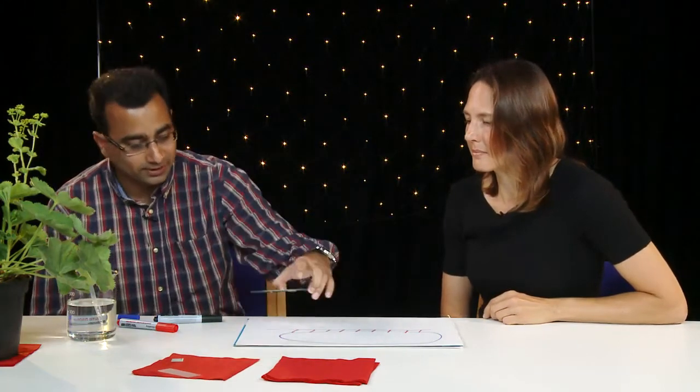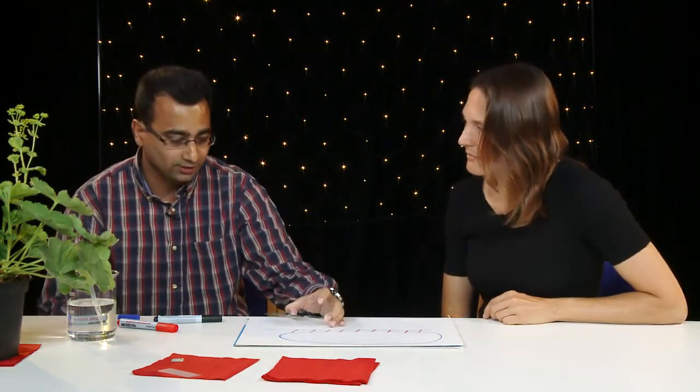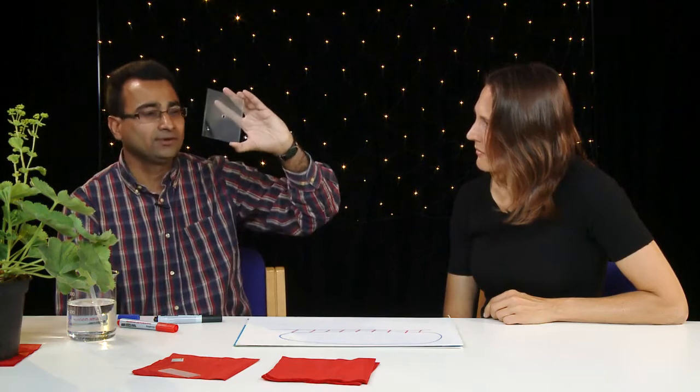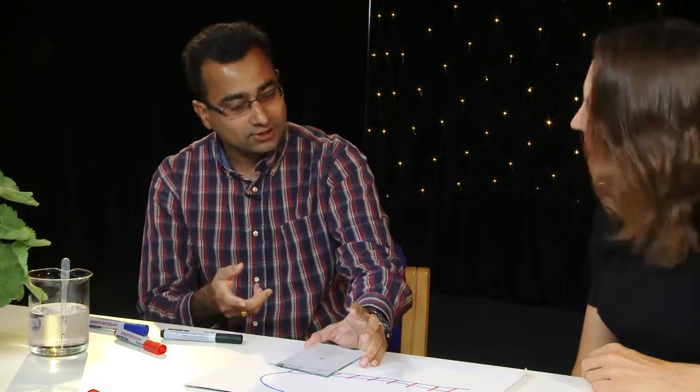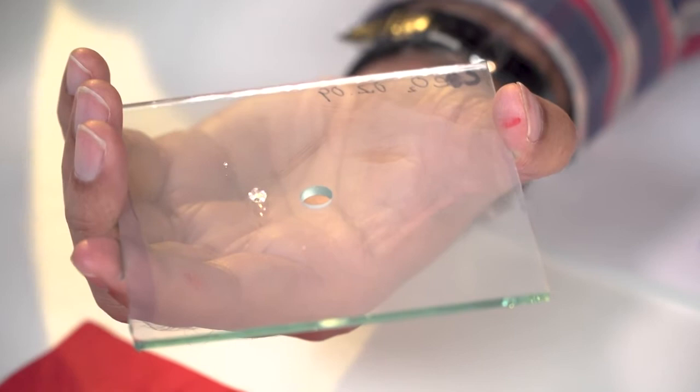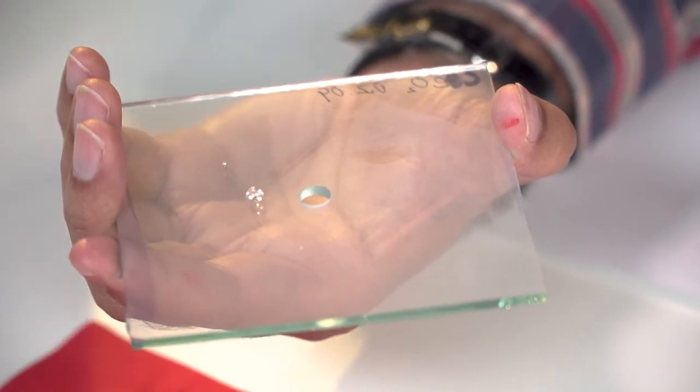So this is an example where we've tried to go one-up on nature, really, where we are not only making this coating, which is super hydrophobic, but we are controlling the texture. Now, the thing about controlling the texture is if we think, if you look at this surface here, it's optically transparent. And that's because even though these are rough, the roughness is controlled. So it's not scattering as much light, which means that it lets light go through,